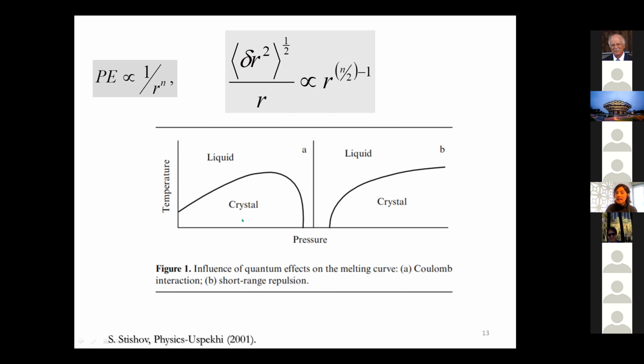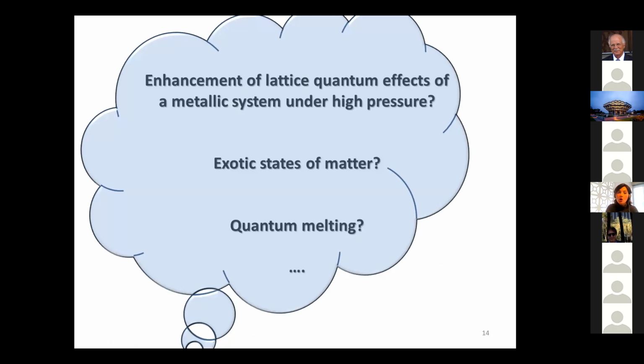And in this case, as you increase the pressure, it's not only the packing that is important, but also disorder coming from the zero point effects that becomes relevant, and you can get quantum melting at some point. So if this zero point effect is enhanced by pressure, you get quantum melting. And this is something that people have been looking at. One of the interesting consequences is: can we get quantum melting in a material? Can we get examples, something like helium 3 and 4, but at high pressures in materials, and what kind of physical properties is that state of matter going to have?